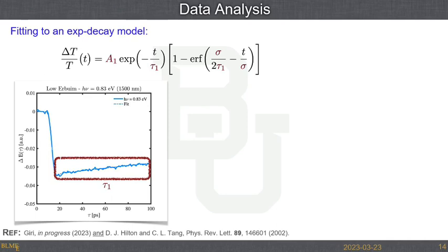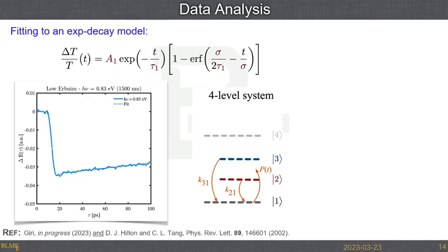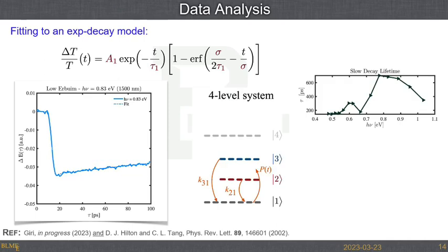And then the parameter that I want out of all of this is this tau time here, which is, if I create this, how quickly can I go before I make this sort of process again? How quickly, once I put the energy into the system, how quickly can it recover from all of that? And then with this 4-level systems approach, I can scan these lifetimes as a function of energy here. This is the photon energy, so this is looking at how high up into this ladder I can propagate.